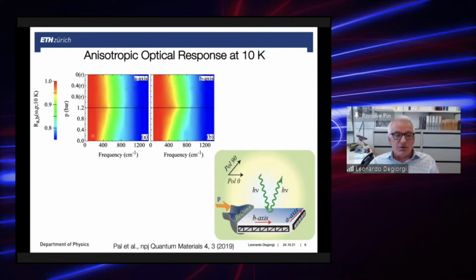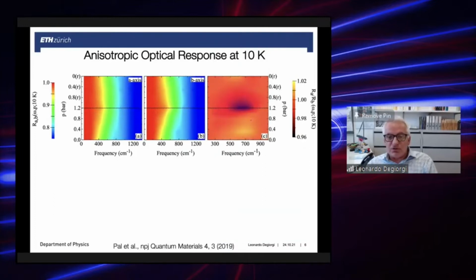In fact, you can observe that the measured quantity reaches total reflection at very low energies. This is the typical signature in optics for the superconducting state. But particularly at the largest applied stress, you can already see here that there's an obvious polarization dependence, which is implying an optical anisotropy, which is stress-induced. And interestingly enough, by releasing stress back to 0, basically you go back to the initial state. So that stress-induced anisotropy is fully reversed. We see here that upon applying a stress, you stress-induce an anisotropy, so a deviation from 1 in this ratio, which corresponds to the isotropic limit. But when stress is released back to 0, you go back to the initial state.